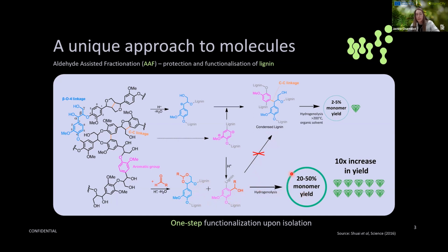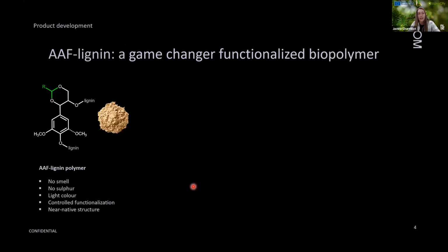And on top of that, what we have is a direct functionalization of the lignin due to the incorporation of this acetal directly onto the structure. And this opens a wide range of possibilities to work with this lignin. So the lignin that we get is typically quite light colored due to the non-condensed structure. We have this functionalization here that we can tune, and we have no smell, no sulfur due to the process